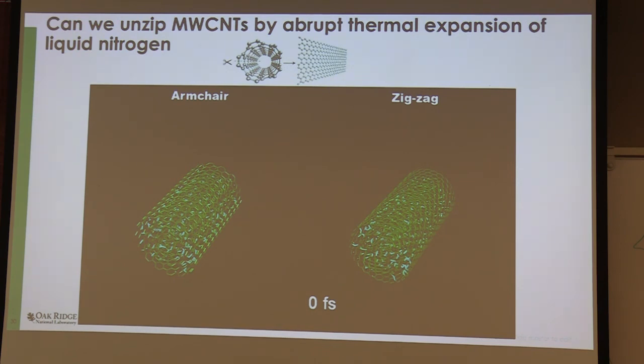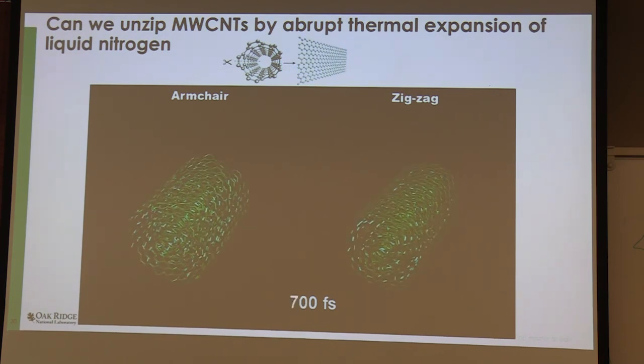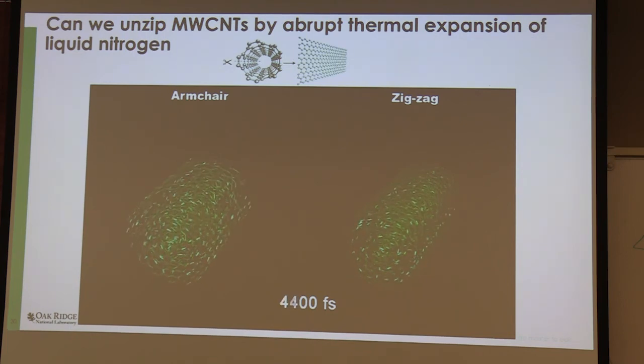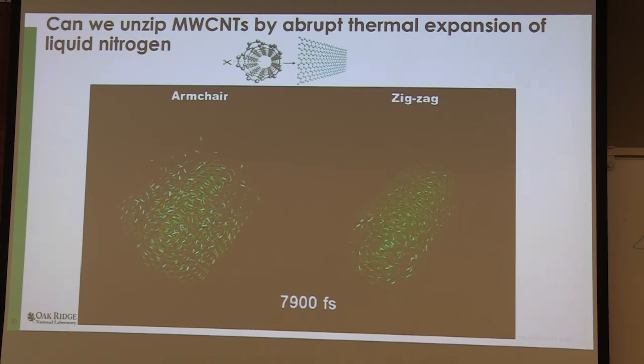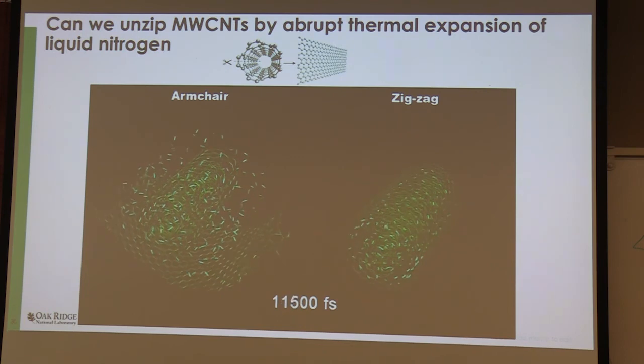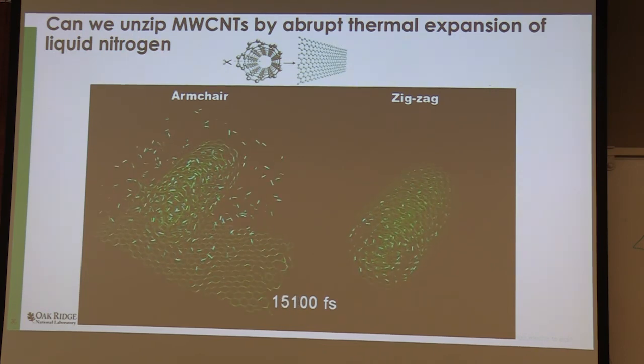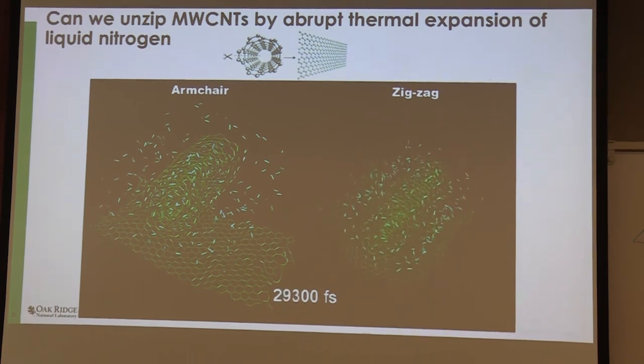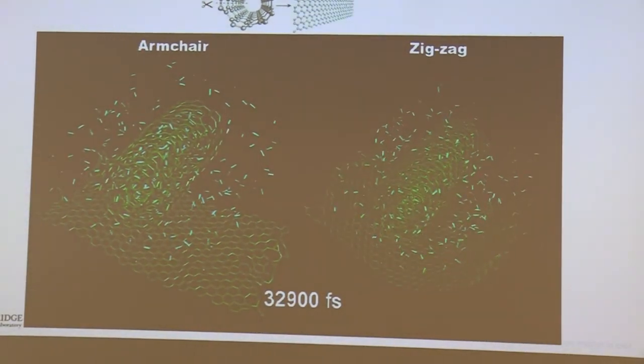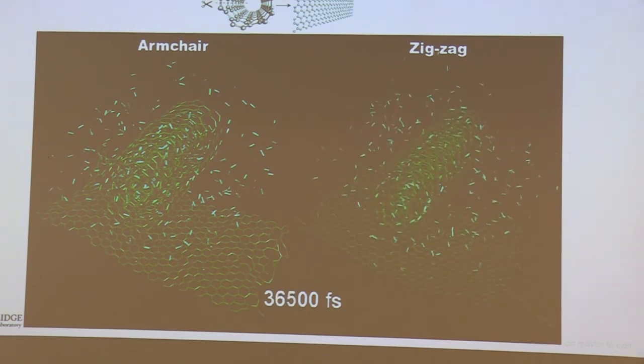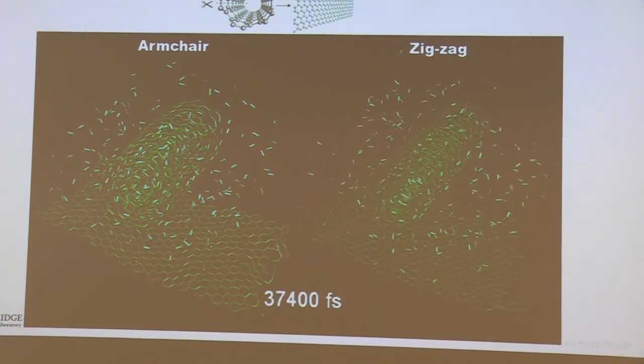And we watch the different types of nanotubes, armchair or zigzag, as a function of time, and see whether we can split them open. And lo and behold, very quickly we split one open, and out, of course, the nitrogen gas goes away. And if you watch far enough, you can split more open. But the first one that splits is the outer layer, which makes sense. It's the weaker layer, and that's the one you split up. It takes a little longer to split a zigzag nanotube, and there's a reason for that. And you can study the fundamental mechanism and where it starts, where the fault is. And you can actually, believe it or not, relate it to continuum mechanics.